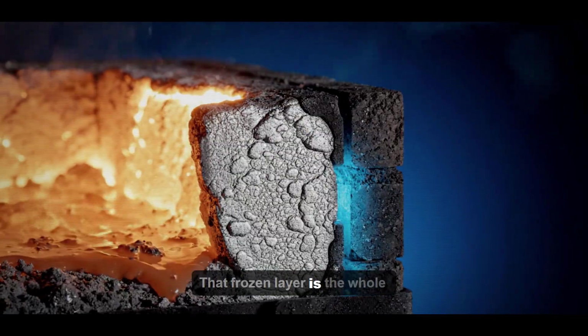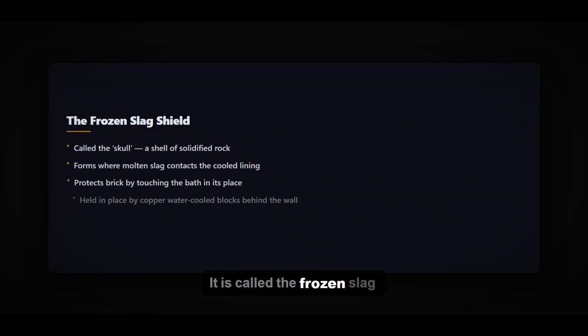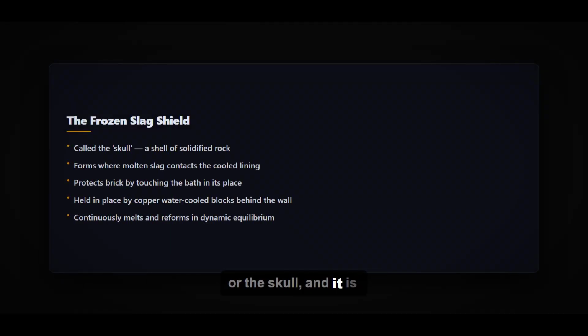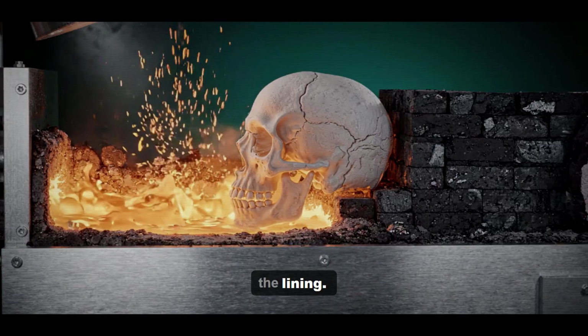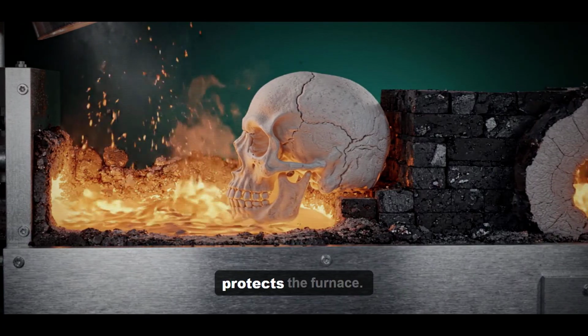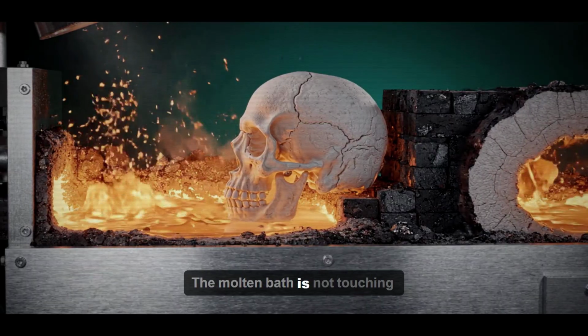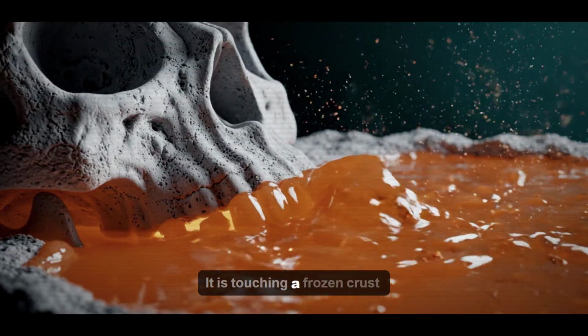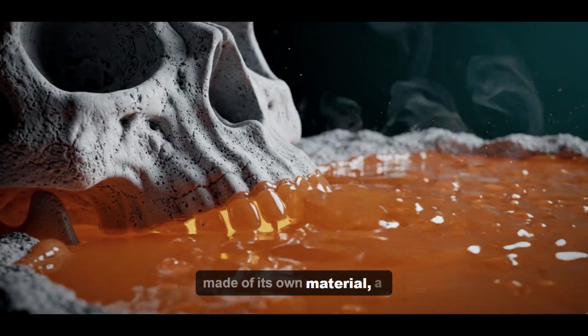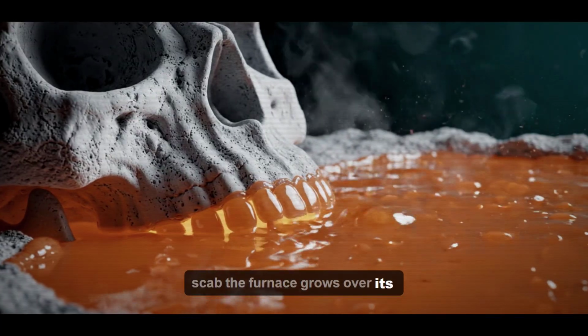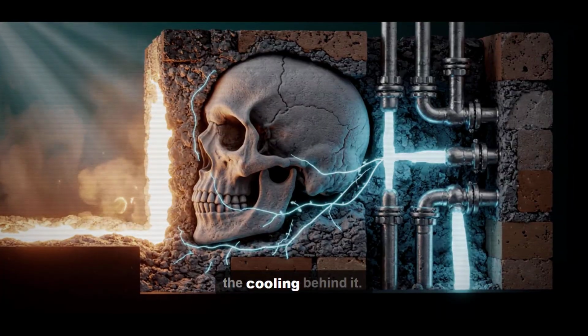That frozen layer is the whole secret. It is called the frozen slag, or the skull, and it is a shell of solidified rock that forms on the inside face of the lining. And this shell is what actually protects the furnace. The molten bath is not touching brick. It is touching a frozen crust made of its own material. A scab the furnace grows over its own wound, held in place by the cooling behind it.